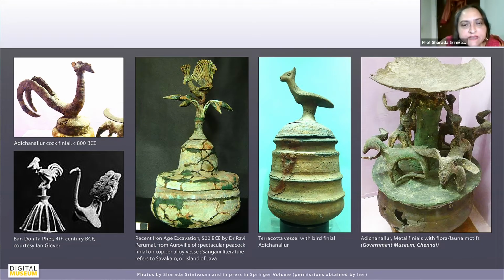We also see other aspects of similarity in the material culture between the finds from Ban Don Ta Phet and the Tamil sites, such as a cock and peacock found at Ban Don Ta Phet. You also see these terracotta vessels with the bird finial. You also see a cock finial, a metal finial, from Adichanallur, which is dated to the early first millennium BC. You also see these metal finials with representations of goats and so on. Another excavation, from Ravi Perumal, showed this urn with a finial and a rather spectacular peacock.